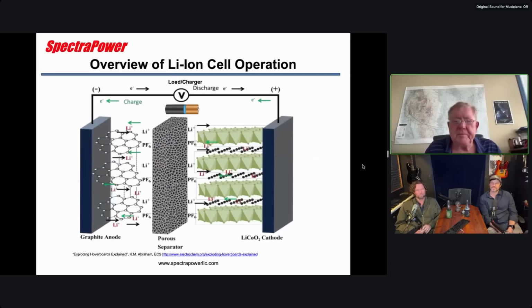In other words, when you're moving this lithium in there, you're stressing it, right? And if you have any impurities, you're going to be stressing it more. The more lithium you move in there, the more you stress it. And so if you keep your charge to no more than 80%, and you keep your discharge to no less than 20%, you're operating in the sweet spot between these two materials rather than stressing. Now, the manufacturer wants to be able to claim he's got real good capacity, so he'll quote the numbers at full charge and discharge.